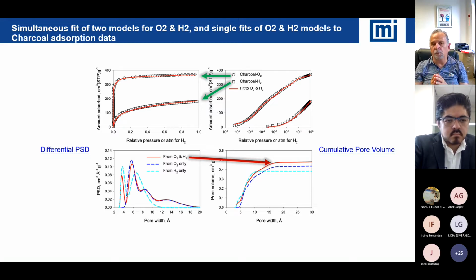Nitrogen versus argon for surface area. People would love to use argon. It has been suggested. The challenging piece of it is, from a literature standpoint, we don't have agreement on, for example, what's the size of an argon molecule on the surface, versus nitrogen, where we all agree to use a specific value. So it makes it very easy to interpret nitrogen surface area data. We all know we're using the same parameters or the same properties for nitrogen. That's not quite the case yet for argon.